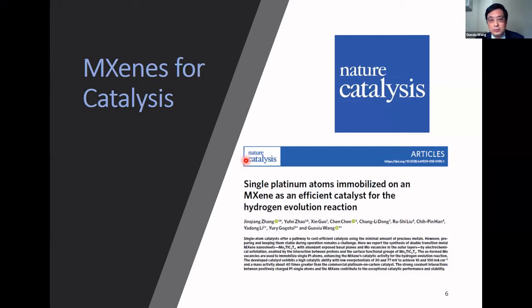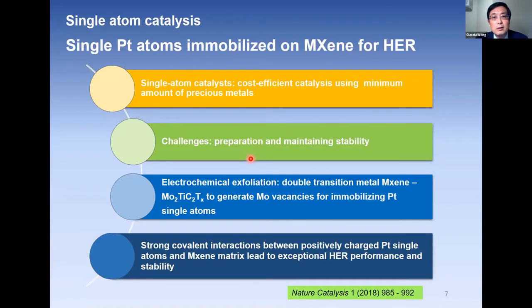In 2018, we accidentally discovered we can deposit single platinum atoms on the surface of MXenes and form a very efficient catalyst for hydrogen evolution reaction. So why did we need to develop a single atom catalyst? Because the single atom catalyst has many advantages, including cost efficiency, using a minimum amount of precious metals. But the development of single atom catalysts faces many challenges, including preparation, it is very difficult to prepare single atoms, and also the difficulty of maintaining stability.